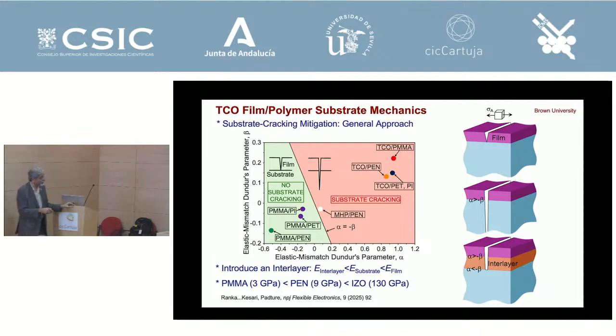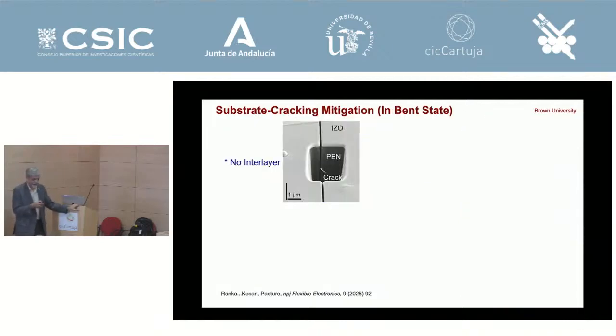When the crack comes from here to here, it's going from stiff to compliant, and so the crack will propagate. But now the crack is going from compliant to stiff because the interlayer is more compliant than the substrate. Now the stress intensity factor actually goes to 0 and the crack will not propagate. We chose PMMA, polymethyl methacrylate, which is about 3 GPa, the substrate is 9 GPa, and the film is 130 GPa, right?